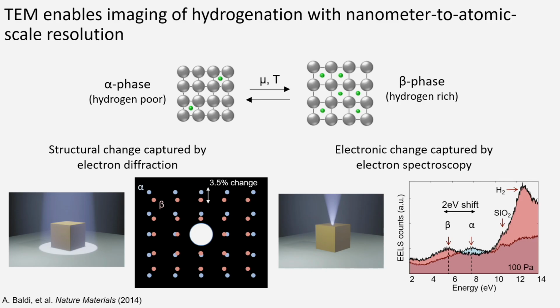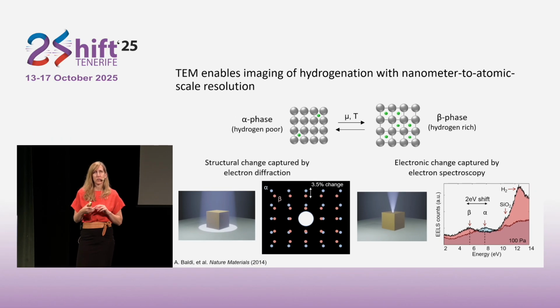And to probe what happens with hydrogen, we use both electron diffraction as well as spectroscopy. So electron energy loss spectroscopy, basically you're shooting your electrons, 300 kiloelectron-volt electrons, through your sample, and then we have an electron spectrometer that can measure down to about 10 millielectron volts difference, which is kind of amazing if you think about a 300 kiloelectron volt electron, and then we're looking just at tiny energy losses down to about 10 millielectron volts. But both of these give us an indication as to a change in the structural property. So hydrogen, when it intercalates into many of these materials, is kind of a misfitting sphere in those interstitial sites, those voids. So it tends to expand the lattice. So from diffraction, we can look at structural changes. From the electron spectroscopy, we can basically look at electronic changes.